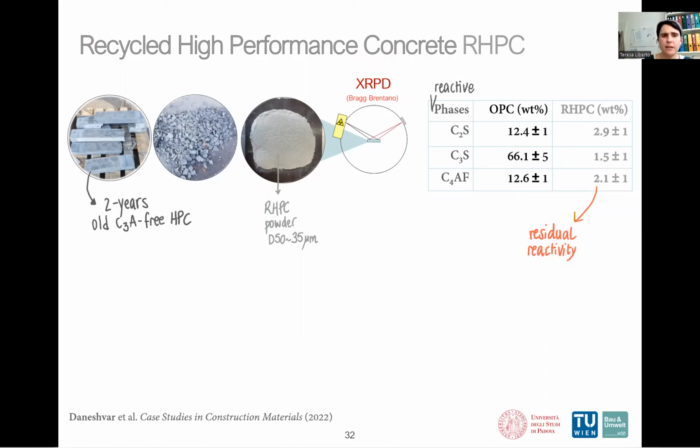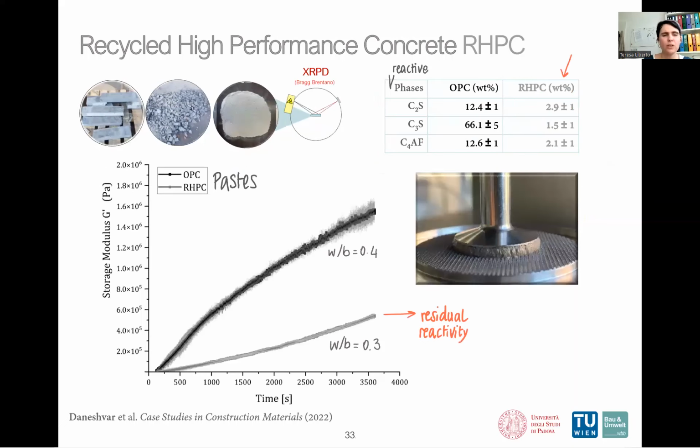And here you can see the reactive phases of OPC, which was used to make this HPC, and our recycled HPC, so after 2 years. Obviously, the C2S, C3S, C4AF are less after 2 years of hydration, but this residual reactivity is really promising. So we decided to do some SAOS, in particular time structuration.